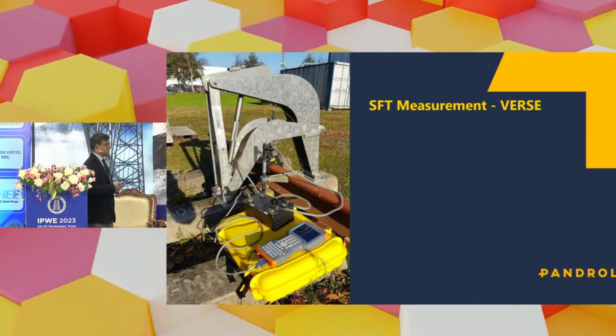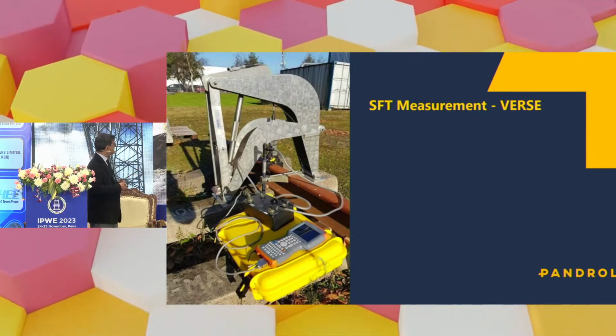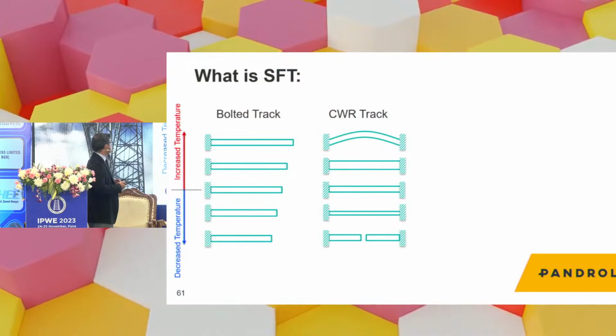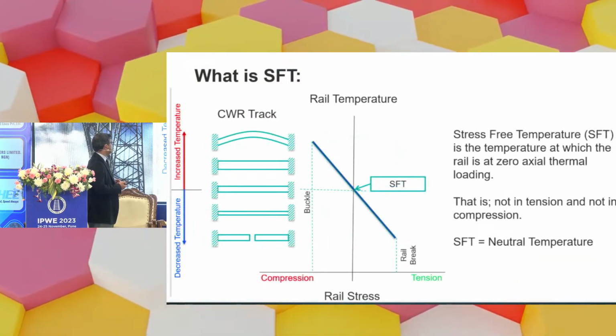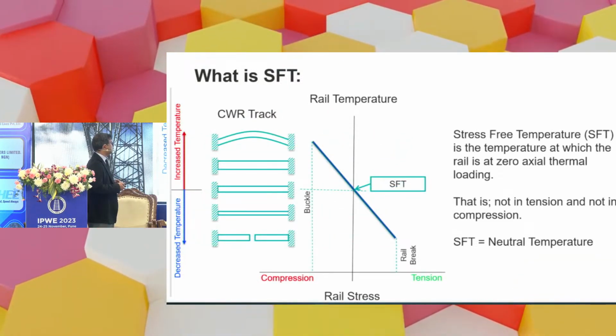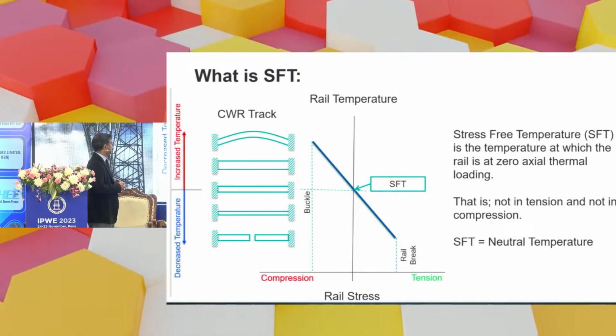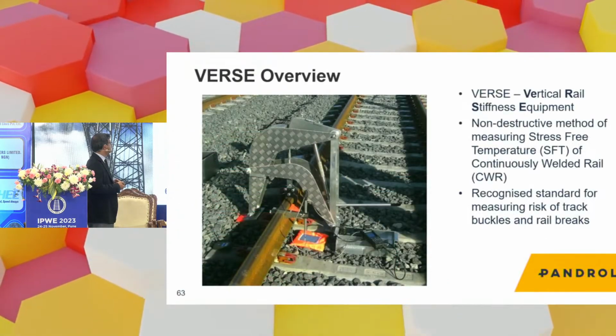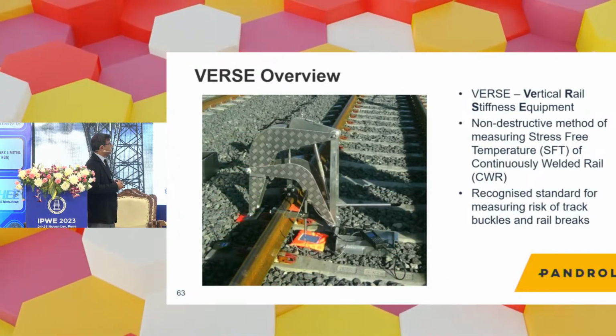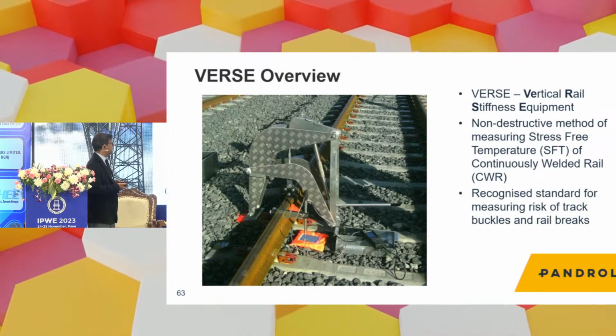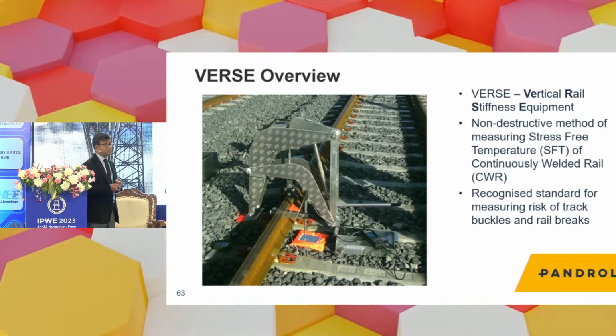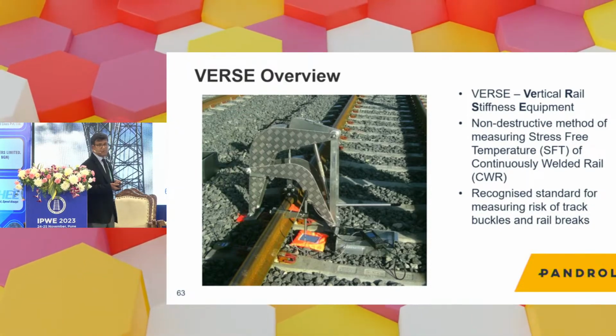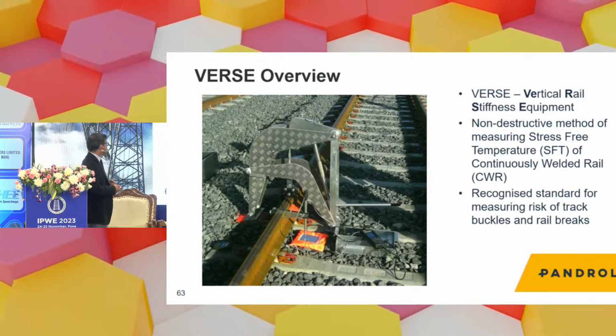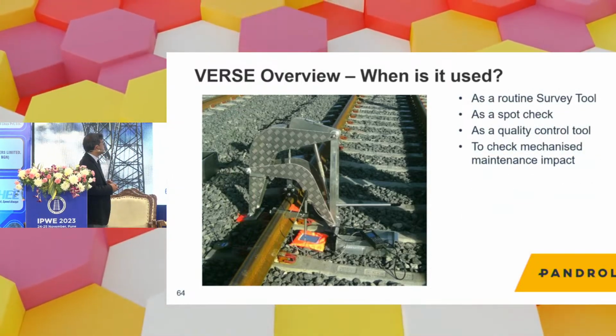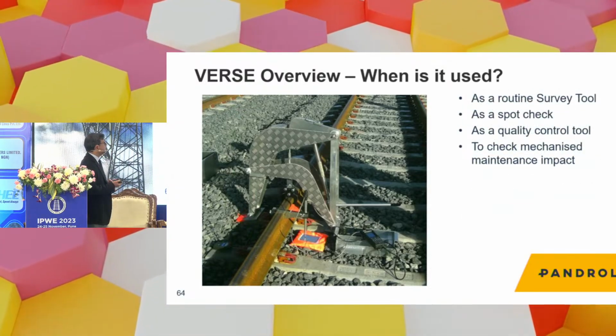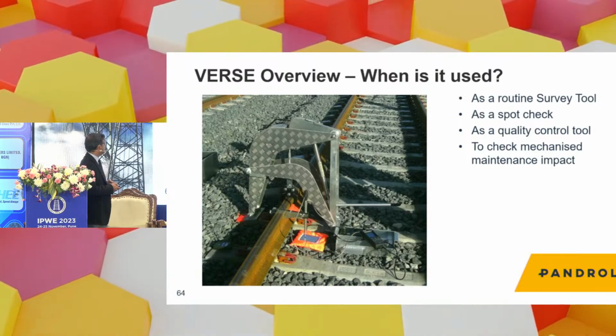This is VERSE. This is a stress-free temperature measurement device, which can measure stress-free temperature for any given track. It stands for Vertical Rail Stiffness Equipment. It's a non-destructive method of measuring stress-free temperature of CWR, and it's a recognized standard for measuring risk of track buckles and rail breaks. It can be used as a routine survey tool, as a spot check, and as a quality control tool as well.